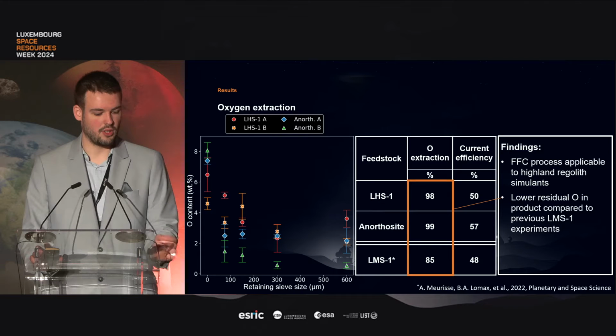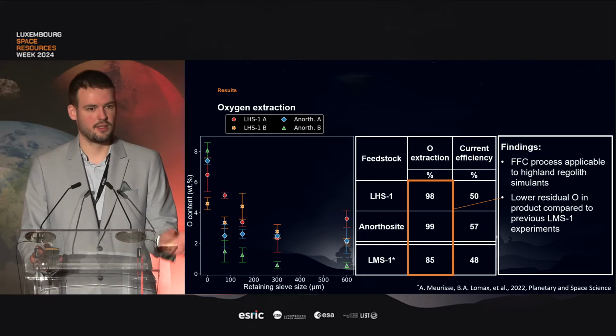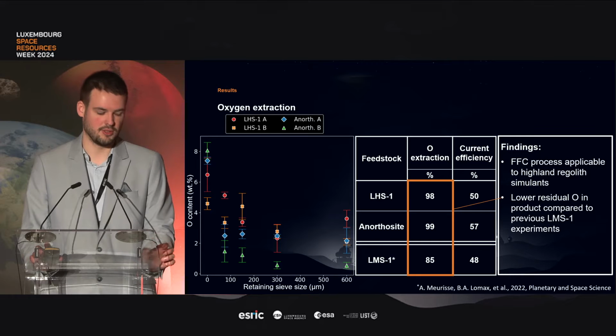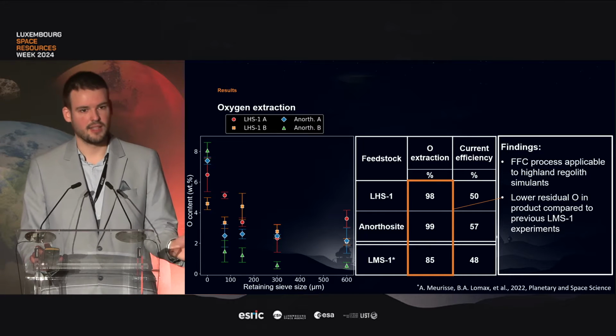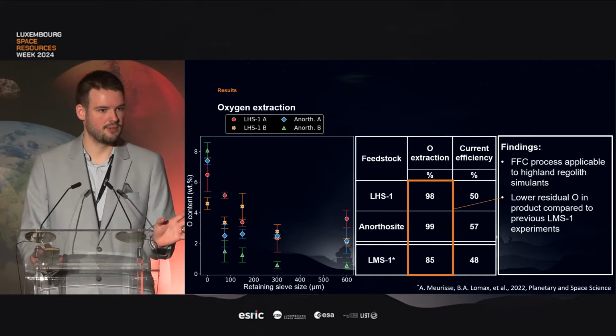And then looking a bit more at the numbers, we can see that the residual oxygen content is very low. So we extracted up to 99% of what was in there. And on the 24-hour period, that's actually quite a bit better than what was observed previously for LMS simulants. Again, the caveat: the setup is slightly different, but it still looks interesting, and we're at least as performant as the LMS counterpart, and probably more performant.